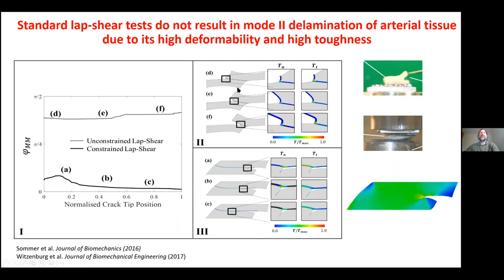A different kind of shear test was tried by Victor Barocas, who's done great work in arteries over the years, but similar problem. So in his test, instead of attaching the top and bottom surfaces to a platen, he leaves them free so this can rotate. But you can still see that this is not a shear. If you zoom in closely here, we get a normal opening here at the crack tip. So this is the bottom experiment. It's almost entirely normal. The top experiment is closer to pi over two, a shear test, but not nearly close enough.